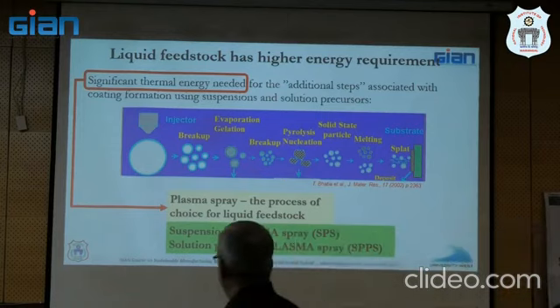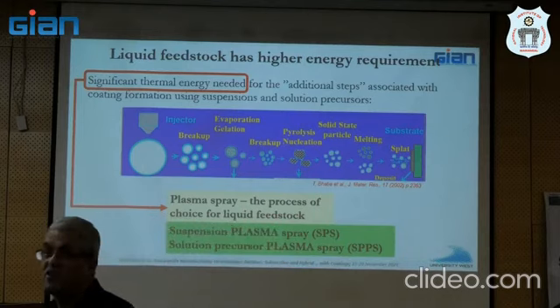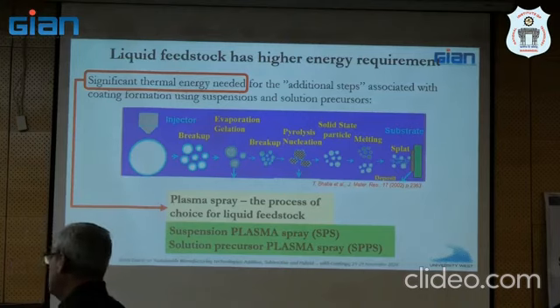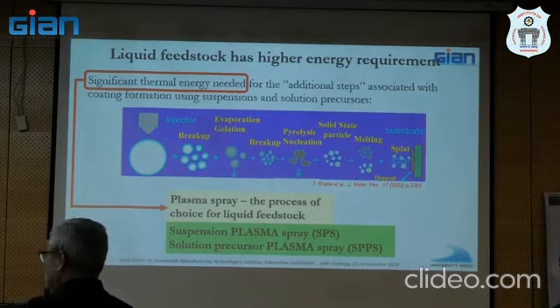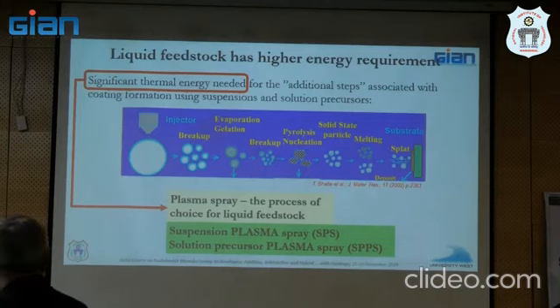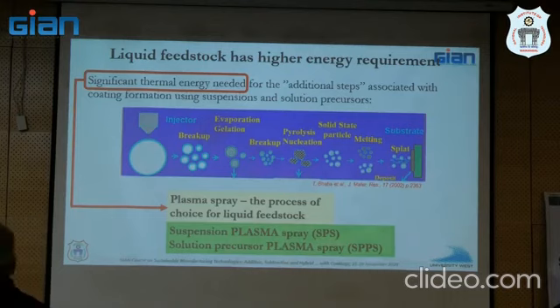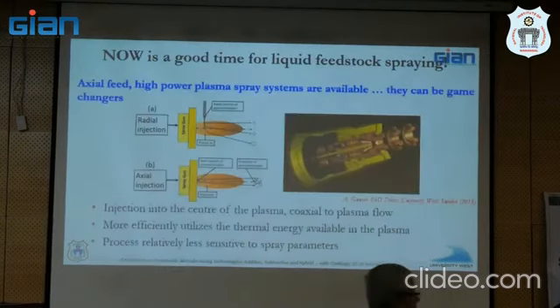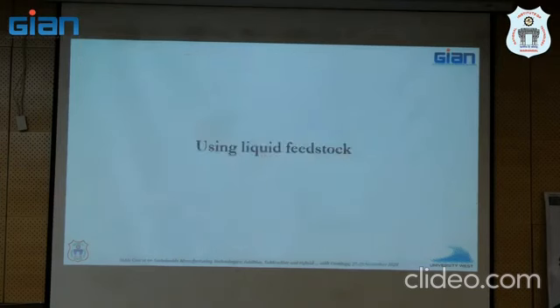So if you look at literature today, you will mostly see these terms used: suspension plasma spray. You will not see suspension HVOF spray or something like that. I mean, you will see some literature, but not so much. Same with solution precursor plasma spray, right? That is because plasma is ideally suited to provide the thermal energy that all these reactions need, right? On top of that, now you are able to feed this feedstock axially through the center, right? So people who were disappointed or unsuccessful with using liquid feedstock earlier, now suddenly can consider going back to liquid feedstock and get some very interesting results, right? And I will show you some of those.